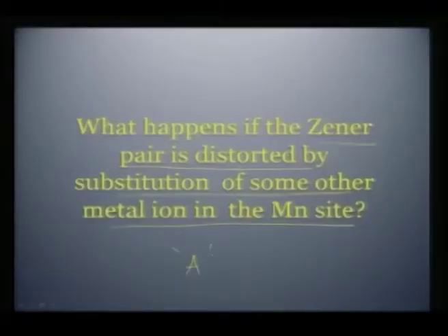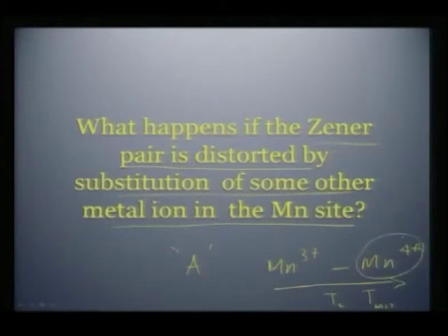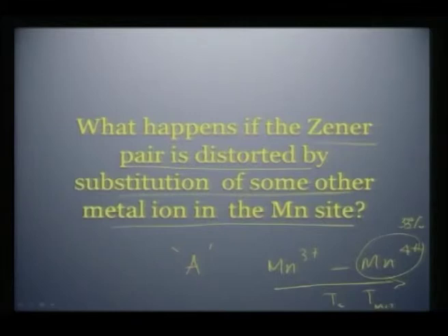As I told you, if you substitute in the A site, that is the lanthanum site, then Mn3+ goes to Mn4+, which is advantageous for us, and therefore you see a ferromagnetic ordering and a metal insulator ordering which is increasing as you generate more and more Mn4+, up to a critical concentration of say 33% manganese 4+. Beyond 33% manganese 4+, you do not see any net change or a spectacular change. In other words, sometimes it becomes detrimental. So, this is the optimum at which you can get a maximum Tc and maximum metal to insulator transition.